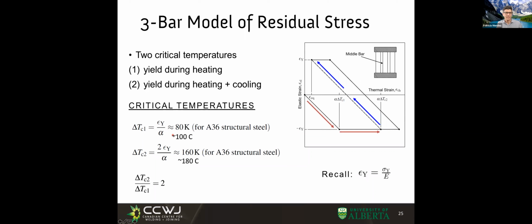All right. So something interesting is you would imagine that the temperature to reach yielding is high, but in reality, it takes very little temperature to reach yielding in most materials. For the case of steel, A36 structural steel, which is what is commonly used, this temperature is of the order of 100 degrees C. So when you're welding something, any point that would make the water boil typically is a point that is yielding. By the way, that's quite far away from the weld. It's not the weld bead, it's actually quite farther away.